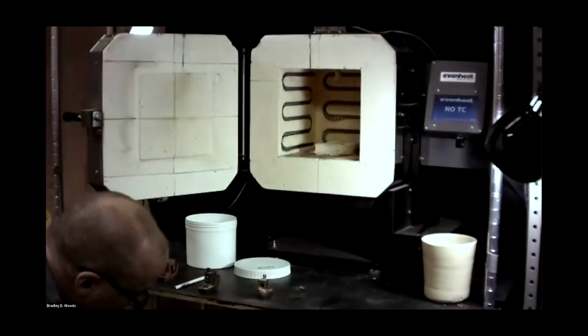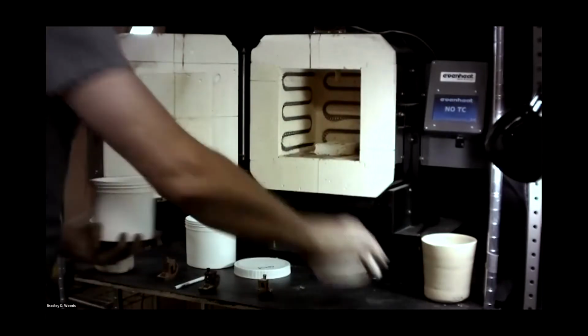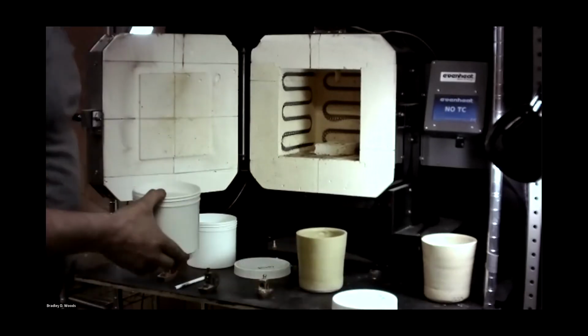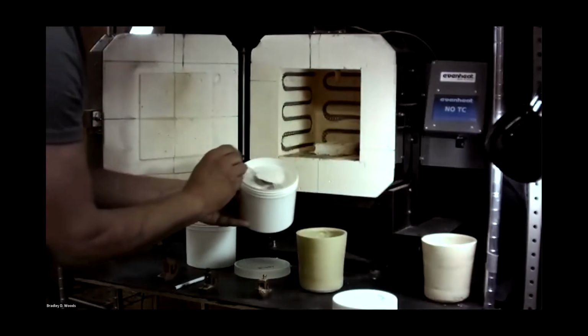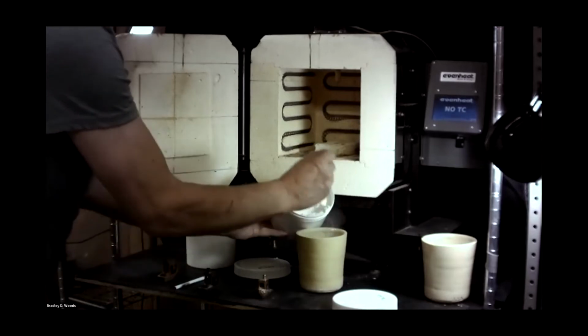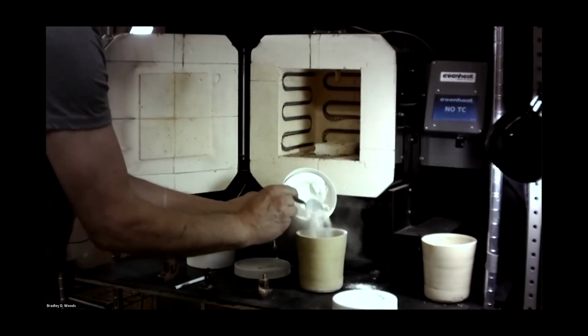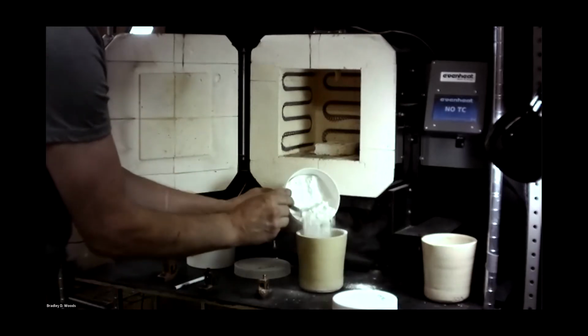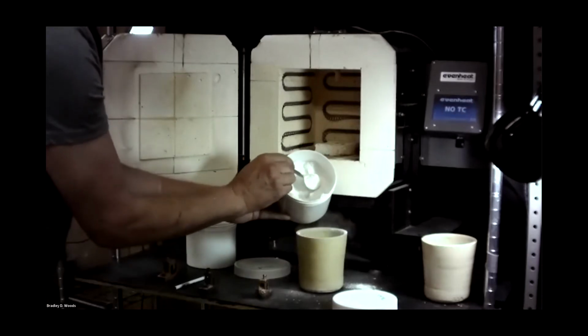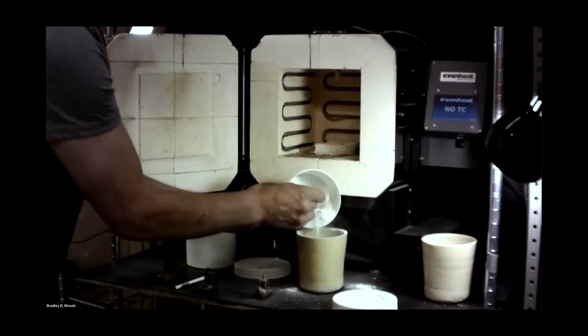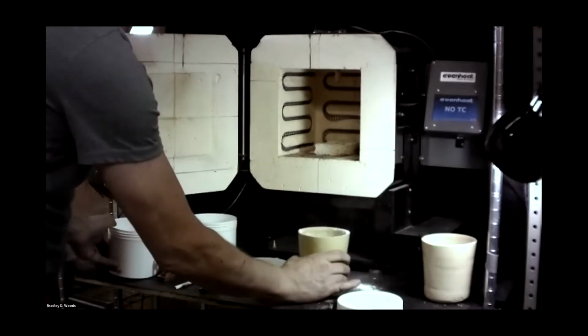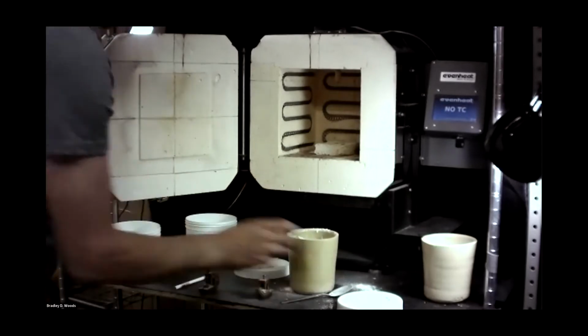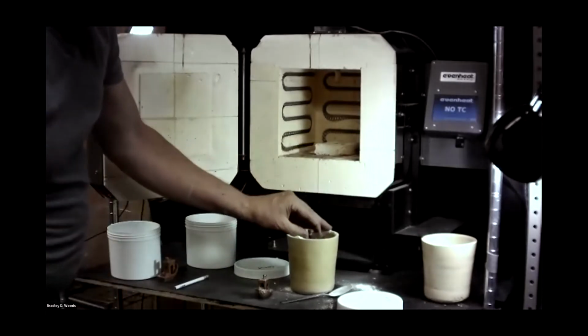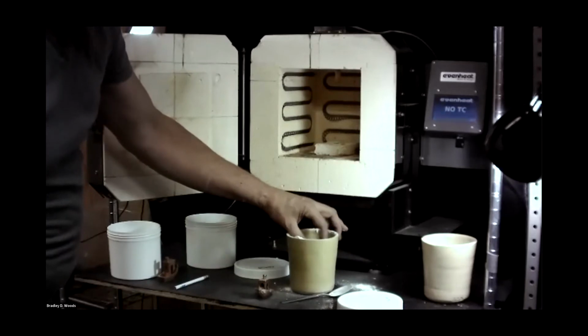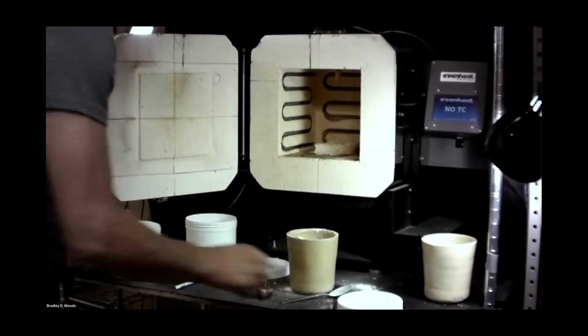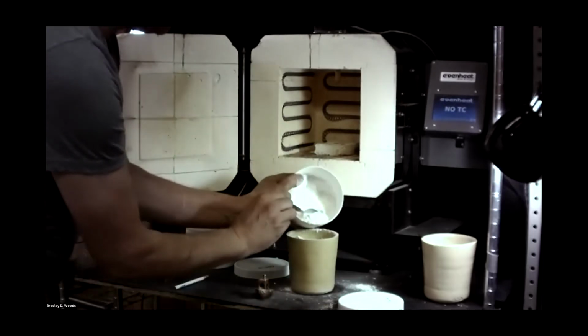Next step. Use the same crucible, and this is talc. And what makes it interesting is that it's so fluffy. I mean, it's been used as body powder for hundreds of years. So that's the whole idea. It yields easily. So when I push on it, it'll move out of the way as it needs to. So in this example, I'll fill this about 1.5 inches down from the top, settle it a little bit. I'll take my brown part, put it down into the talc. It pushes easily, the whole thing yields, move it around and make sure all the voids are filled. Put a little bit more on top of it.